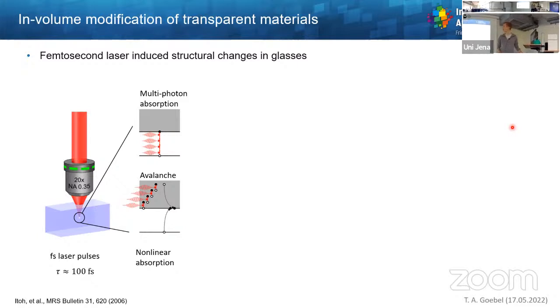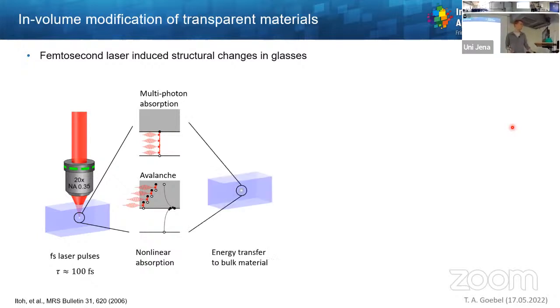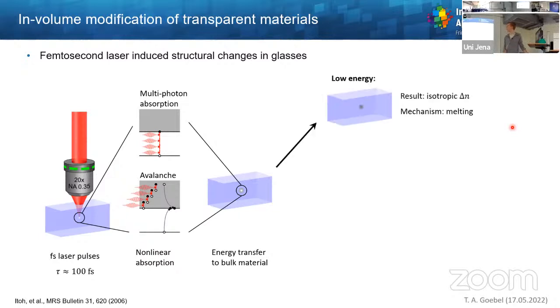So what we have is, in the first step, we have a multi-photon absorption occurring, and once enough electrons are coming up from the valence band into the conduction band, then we can have a further absorption, and if these electrons get enough energy, they can have an avalanche ionization process, and both together will deposit energy into our focal region. And now, a bit depending on our energy regime, we have different effects occurring.